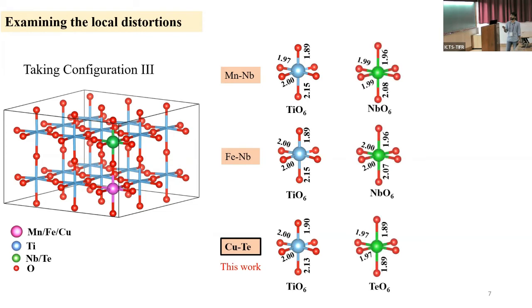co-dopants. Now, if one goes to copper and tellurium, that is the other co-dopant, one finds that in case of niobium, both manganese-niobium and iron-niobium, there is a considerable off-centering along the c-axis. But in case of tellurium, one finds a non-polar distortion, not an off-centering, in contrast to the manganese-niobium and iron-niobium.